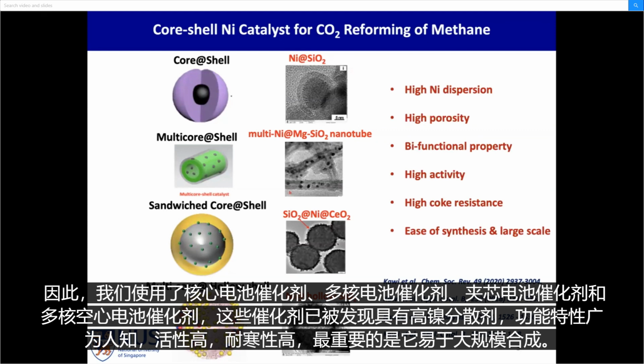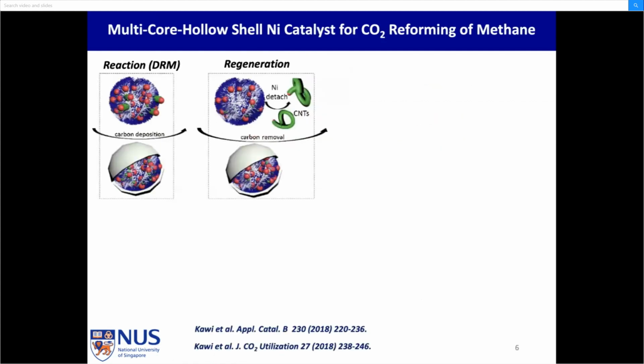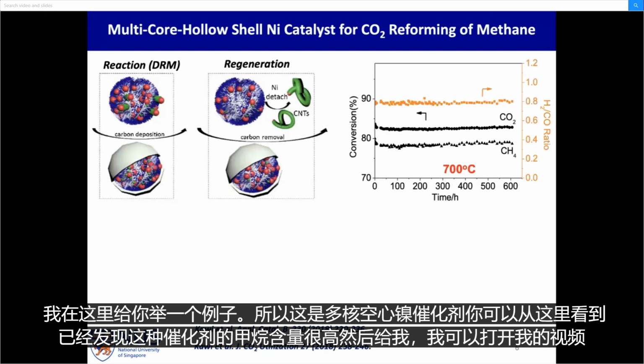Our catalyst has been found to have high nickel dispersion, high porosity, bifunctional property, high activity, high coke resistance, and most importantly, it is easy to be synthesized on a large scale. I'll just give you one example here. This is the multi-core hollow shell nickel catalyst. You can see from here that this catalyst has been found to have very high methane and CO2 conversion, almost reaching equilibrium conversion, and almost no coke formation for more than 600 hours, because of the silica shell surrounding the catalyst, and the catalyst can be fully regenerated.